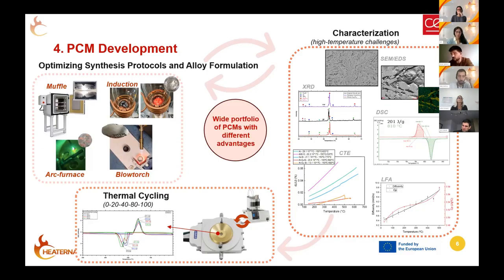This characterization not only confirms whether we have achieved the expected alloy, but it also allows us to obtain the key thermophysical properties that fit the thermomechanical models. The characterization includes microstructural and compositional analysis of the alloy, as well as measurement of the coefficient of thermal expansion, latent heat, specific heat, thermal conductivity, diffusivity, and more.